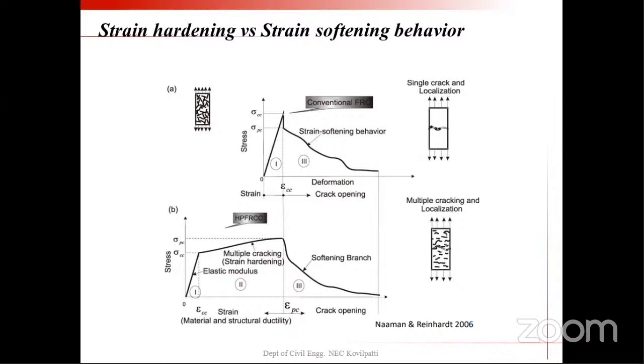But if you want to discuss the energy absorption mechanism, you can see multiple crack localization takes place. So the fibers bridging across the multiple cracks will improve the tensile strength. The tensile strength of the composite is further increased and it will take load. After that, if any one single fiber attains localization, the crack gets widened, meaning other cracks get closed, and again the same softening behavior is repeated. So in strain hardening, the stress is increasing. After that, multi-cracking takes place, which will improve the tensile strength of the composite. After the increment in stress, if there is any opening in one bigger crack, that will become the single localized crack. That will get widened while other cracks may get closed. After that, it will not take any stress, and it will reach the zero value.